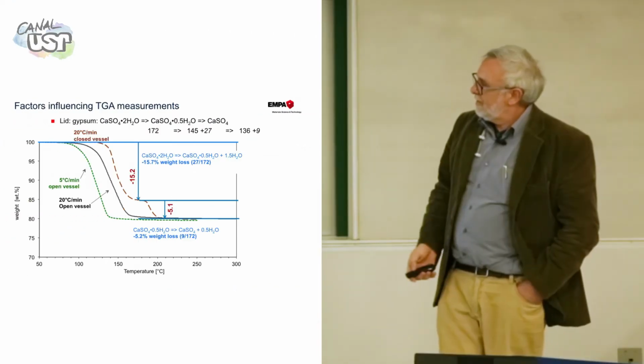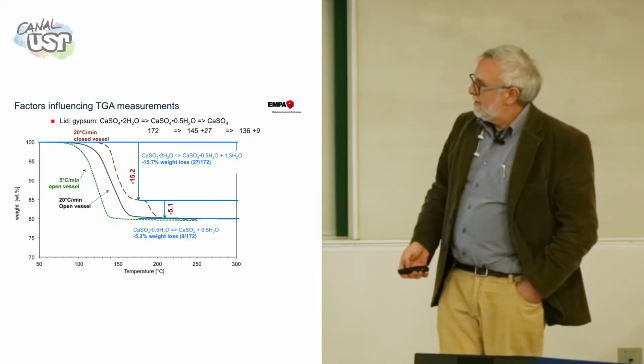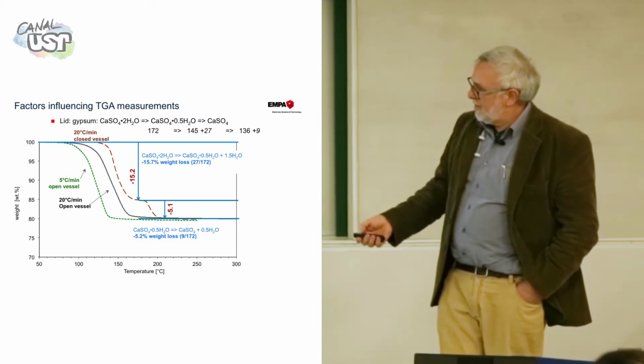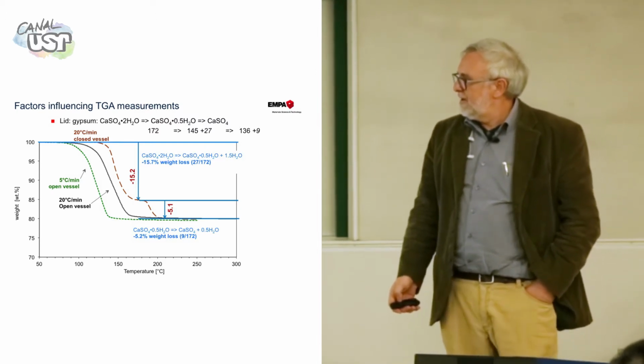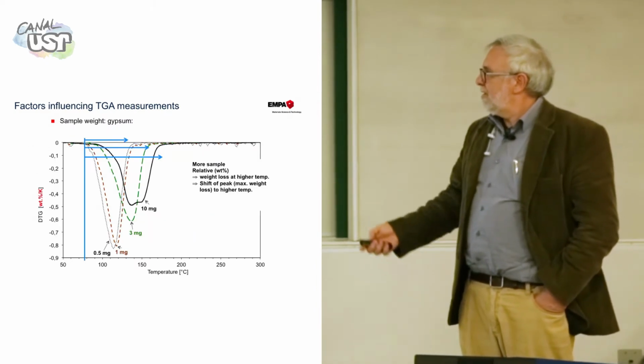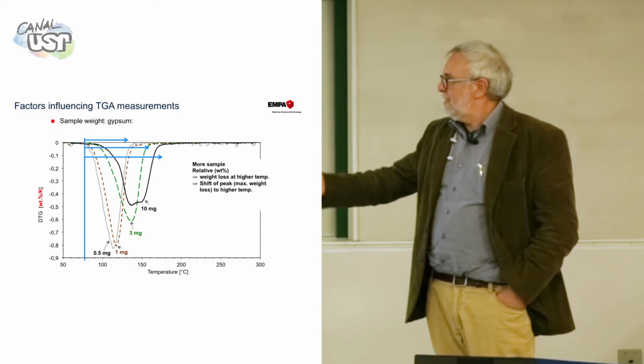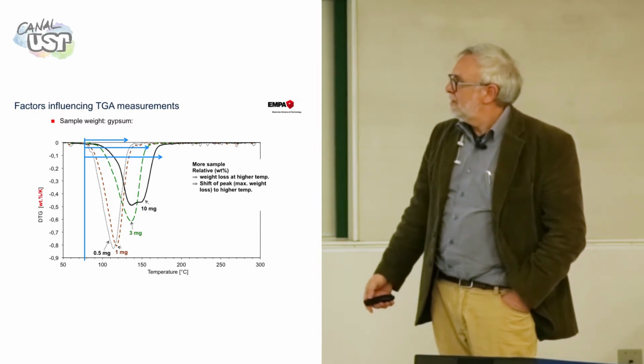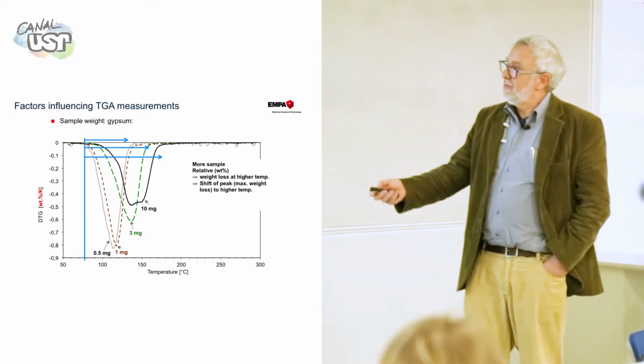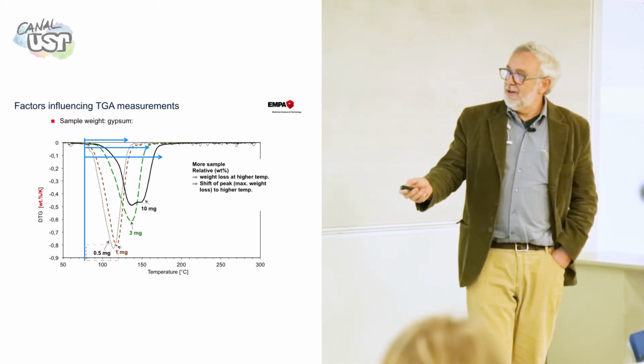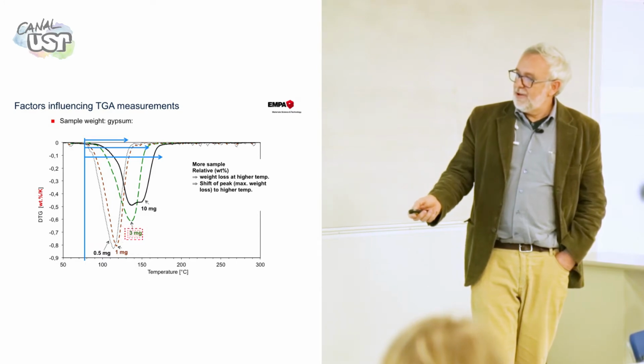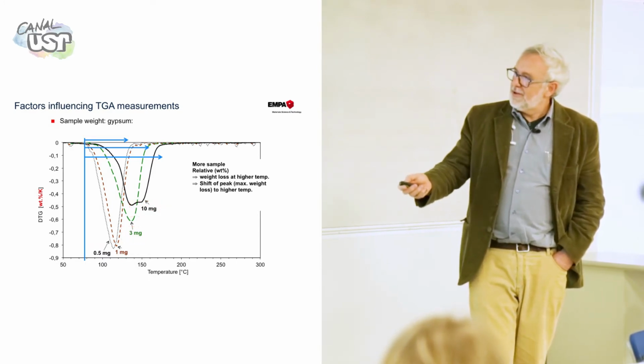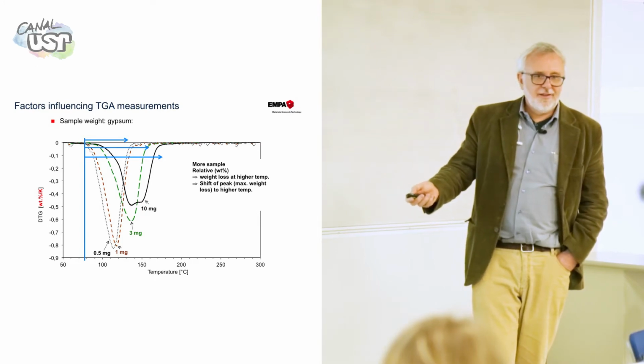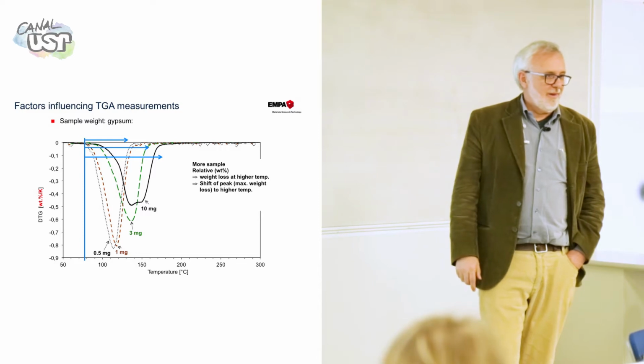So this is the amount of gypsum you have, and this is the amount of hemihydrate in the system. So you can easily see the proportion if you do the right calculation. Here is the sample size. So 0.5 milligrams you are here, 3 milligrams you are here, 10 milligrams we are here. You see, things are starting to show up. So it's better to have a little bit larger sample.